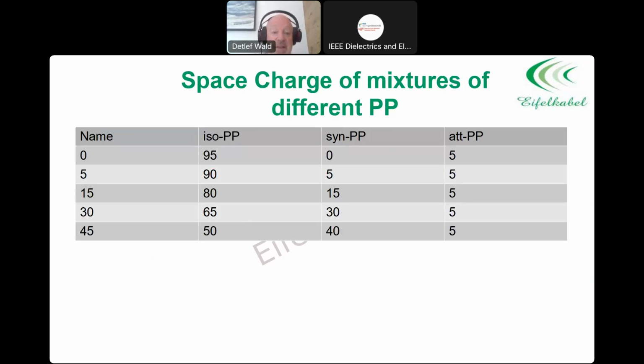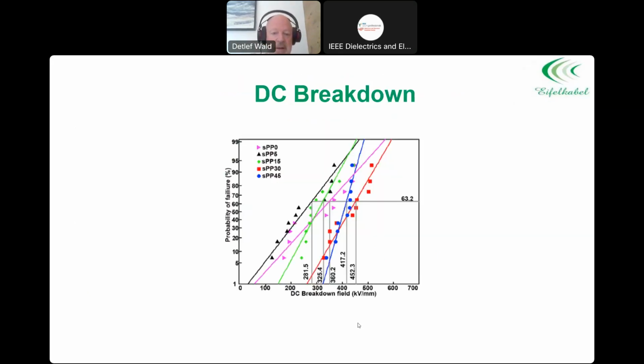When we're coming now to that, naturally here also people have looked into polypropylene compounds, mixing different polymers together. In this test, they only mix different polypropylenes together: isotactic polypropylene, syndiotactic polypropylene, and atactic polypropylene. The atactic stayed always at 5%. So what was varied here was an increase of syndiotactic polypropylene, and naturally the isotactic polypropylene was then replaced, and the results are here below. So also here you have an optimized value, the pink one in the middle. So at first you are decreasing the electrical property, the DC breakdown, and then you can increase it again if you're going over a certain threshold.